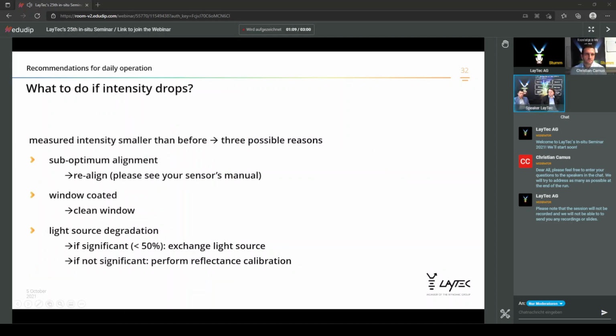Well, what to do if the intensity drops? Suboptimum alignment means you need to realign it. Please refer to the manual or contact LayTec, contact Aixtron, the tech support, or the LayTec service partner if you are in a region where we have our service partners. Well, if the window is coated, for different technologies when I have done that, it was always a wet cleaning. So you etch the viewport window in some kind of acid mixture. But I saw now also some dry cleaning methods. Both are possible.